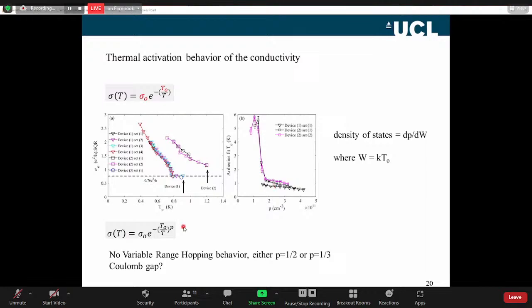The other point is what we don't see is any other type of conductance behaviour. If you look in the literature, you might say, oh, well, it just goes over to being hopping, variable range hopping. It's variable range hopping, but it isn't. With variable range hopping, conductivity is given by an Arrhenius behaviour, but with an extra power p in there, either a half or a third, depending on the type of variable range hopping. If it was Mott variable range hopping, it would be a third power. If it was Efros-Shklovskii, it would be a power of a half. We don't seem to get this.